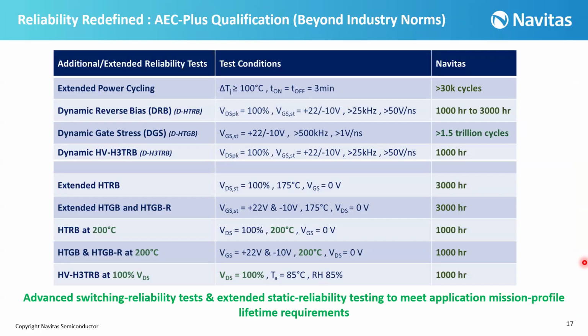Here is the result, or it's better to say this table shows the reliability for this technology based on the AEC, but these devices are not only passing the AEC, but also they are beyond the industry norms. So we named it AEC plus qualification. All the green numbers here are the numbers that are higher than the standard that silicon carbide devices need to provide. For example, for power cycling, we have more than 30K cycles. Dynamic reverse bias, or DRB, 1,000 hours to 3,000 hours, which is a huge time for the DRB.